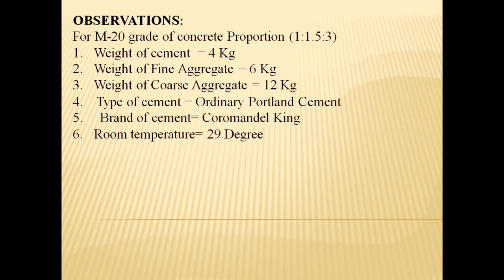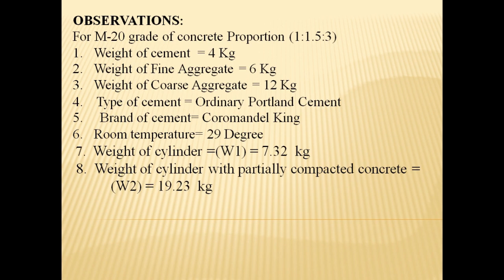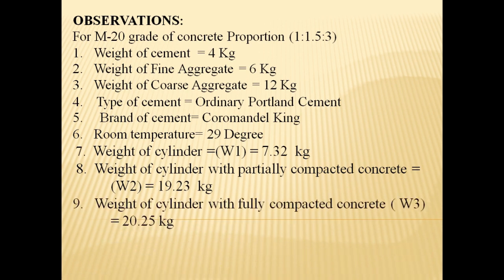The room temperature is 29 degrees. Weight of the cylinder, that is W1, equals 7.32 kg. The next one, weight of the cylinder with partially compacted concrete, which is W2, equals 19.23 kg. The next observation is weight of the cylinder with fully compacted concrete, which is W3, equals 20.25 kg.